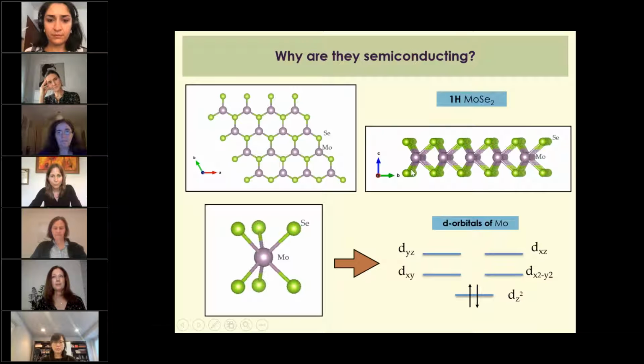where if you look at them from the top, the top view has these atoms arranged in a hexagonal form, and I'm going to focus my talk on molybdenum diselenide, where you have a central layer of the transition metal atom, and you have a layer of these anions, which are the seleniums above and below. And the local crystal field around this central molybdenum atom gives rise to a lifting of the degeneracy of the d levels. And so essentially, one has a semiconductor just because each molybdenum atom over here has a formal d electron count of 2. And so these levels are filled up.